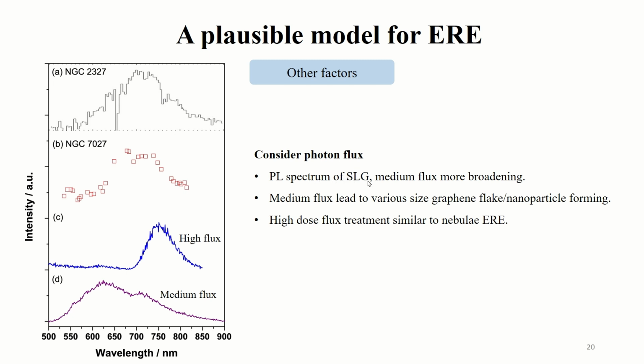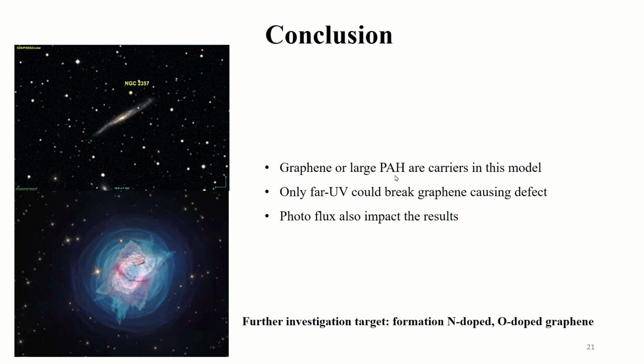PL spectra of single-layer graphene medium flux are more broadening, and medium flux lead to various size graphene flake nanoparticle forming. And this high flux treatment is similar to nebula like this NGC and this NGC. Both of these are nebula, so graphene might be the carrier of ERE. Here is my conclusions. Graphene or large PAH are carriers in this model. Only far UV could break graphene, causing defects. Photon flux also impacts the results.